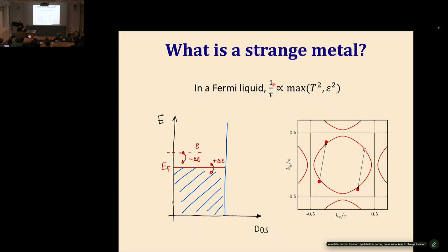This can be measured directly in ARPES experiment, but if we think about transport, that's not enough. Transport is really measuring the rate in which the electrical current, which is a collective phenomenon of all the electrons, is decaying, not just a single quasi-particle. To have this T squared dependence of the single quasi-particle scattering rate appear in the resistivity, we must have some mechanism to relax the total current or the total momentum of the electrons. In this sort of example of Fermi surface, that would come through umklapp scattering. You can scatter into the next Brillouin zone, which really means that the total momentum is not conserved.